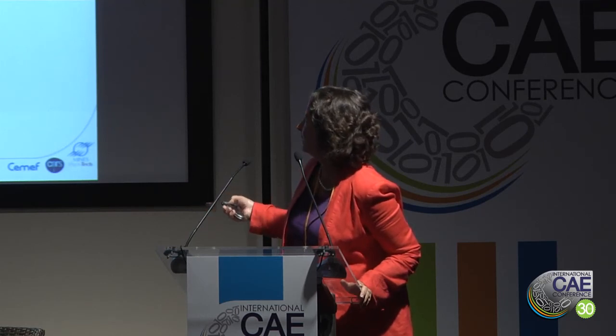Sorry about that. It's also very important to have a real image of the microstructure and afterwards to pass on this microstructure a finite element mesh. So here we have a real image. We treat this image in different ways, and if we see this red square, we have here the image of the finite element mesh corresponding to this one. So this is very important in order to see the evolution of strange phenomena like second phase particles during the simulation. So I don't have time, I know.